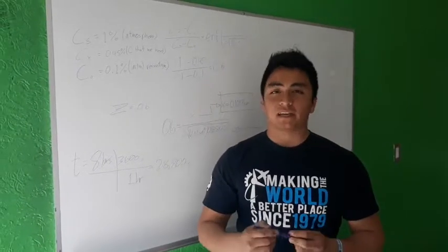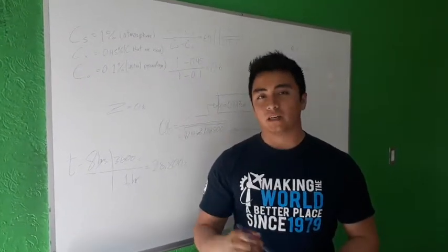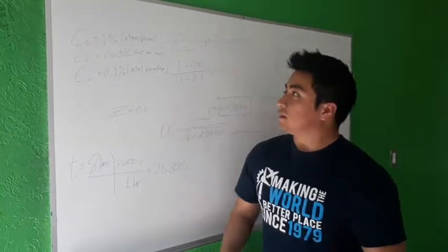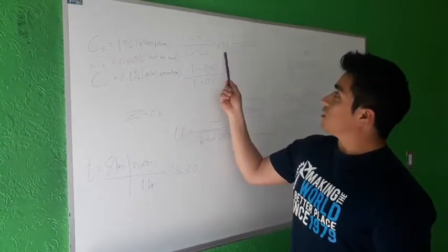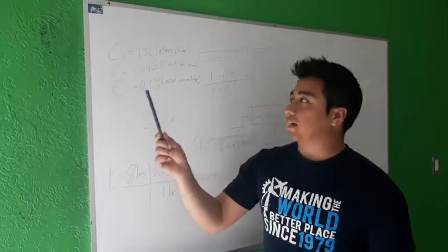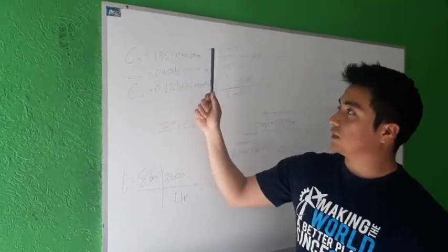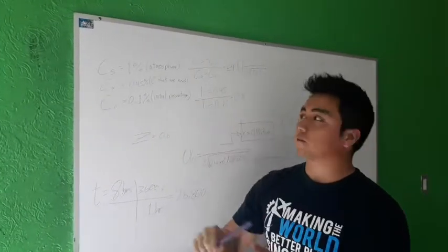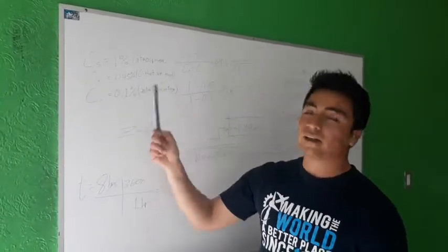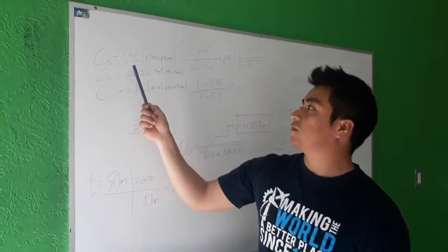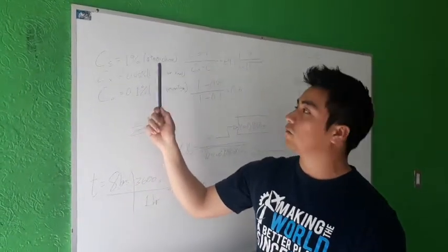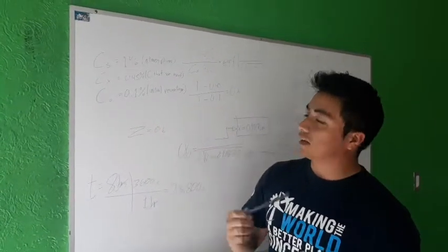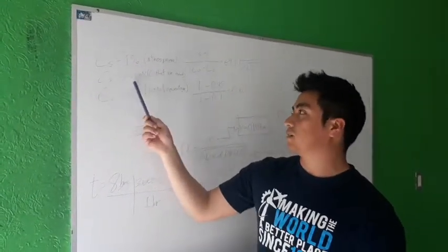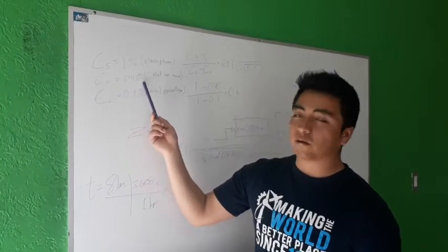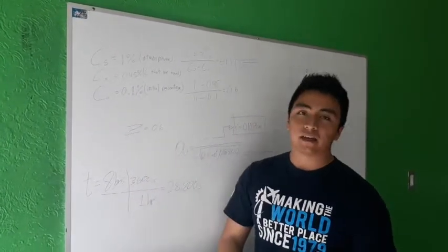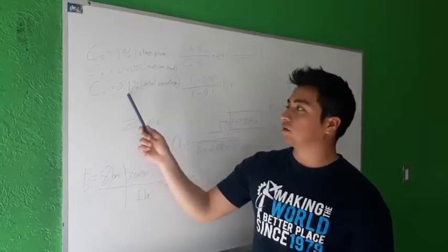Now I'm going to explain how we calculate the depth of the carbon layer on our pieces. We're going to use this formula, and we have this data. This is the percentage of the atmosphere at the surface of our material, C sub S, where we have 1% of carbon. The carbon that we need is C sub X, that is 0.45%, and our initial carbon percentage is 0.1%.